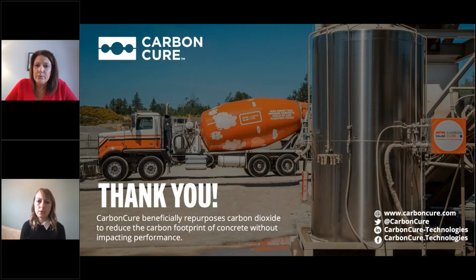And Shannon, what do we notice about CarbonCure during the finishing process? So examples are set time, bleed water, surface porosity, early age PSI. There's a question we get, and we have identified some of the most challenging finishers in the industry and have given them trucks with CO2 and without CO2, and we have yet to find one that can identify which truck had the CO2 in it. So there is not a noticeable difference at all in any of the fresh properties.